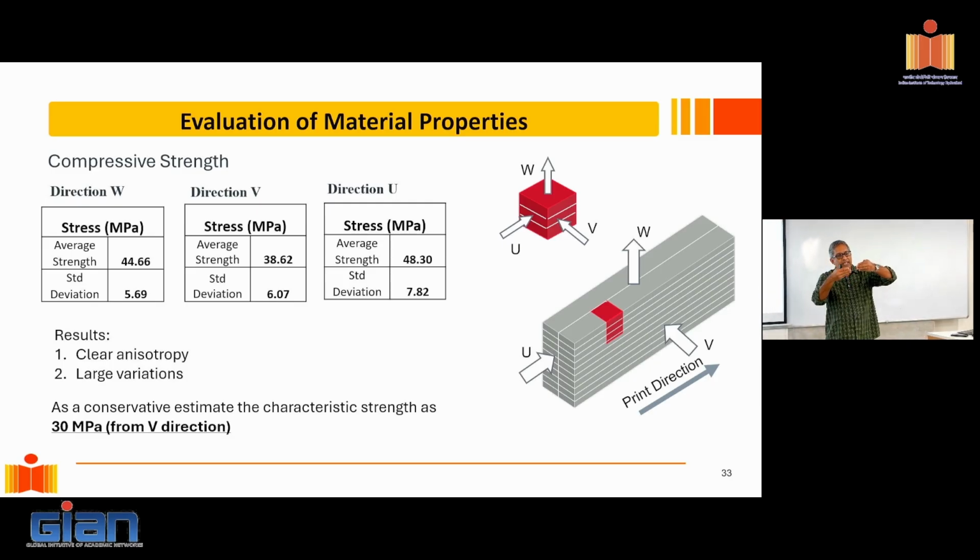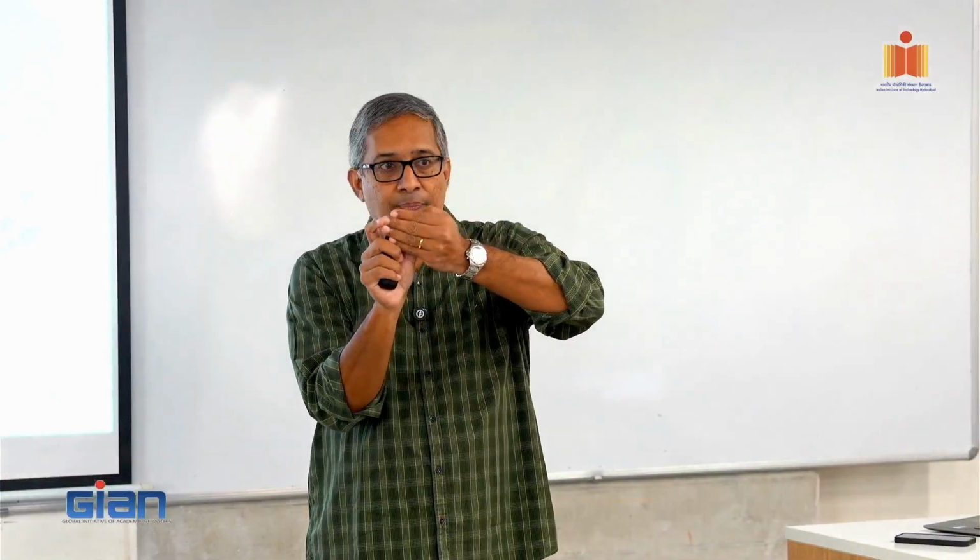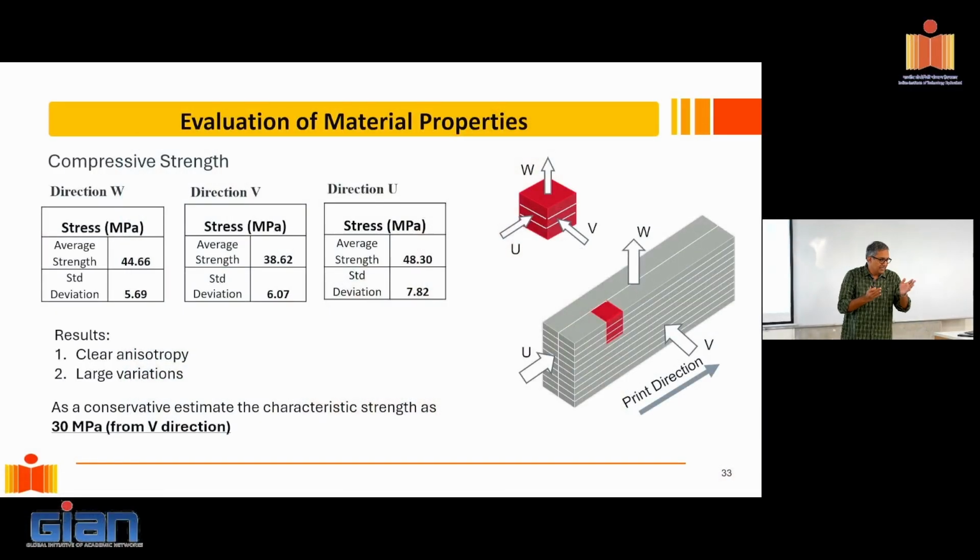If I test them in the direction of the deposition of the material, that's where it is the strongest. If I test it perpendicular to the interface, that's where it is the weakest in compression, right? So mechanics, yes, still has to be put in place, but that is what we're dealing with. So now, if I was to port what I know from structural mechanics, or what we know about strength